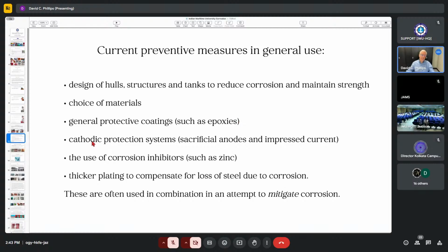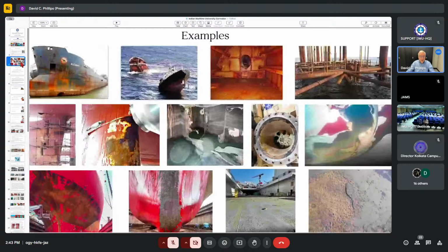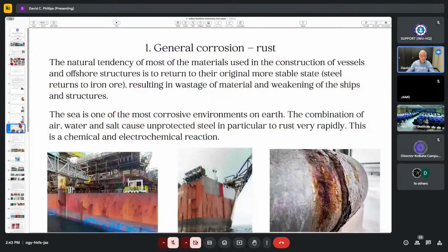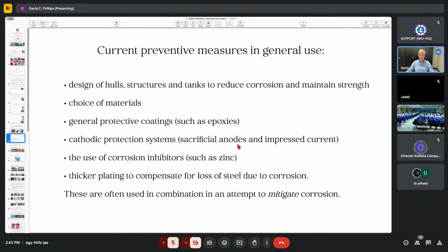There's a lot of technology around cathodic protection systems. The two main types: you either stick sacrificial anodes on the hull or part of the ship. A sacrificial anode is a chunk of metal which is less noble than the steel of the hull. So if there's going to be corrosion, it's going to happen first to the sacrificial anodes. That's the theory, and it actually works. You see these zinc anodes on ships. Well, we'll come to that later on. But this is common. Zinc sacrificial anodes are common.